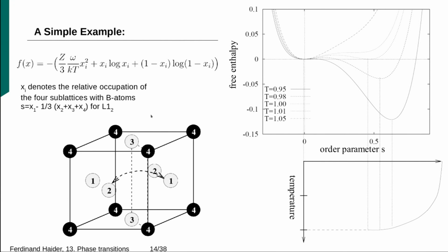That's a reasonable definition. By going through a very similar calculation, you obtain a free energy now of this form here. Sorry, again I changed the terms here. So xi is the occupation of the sublattices, that's as before - there's a sum over i missing. Omega is what I called epsilon before, and these are the terms for the entropy here. Sorry, I forgot the sum over i here.